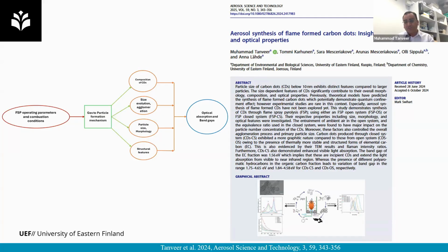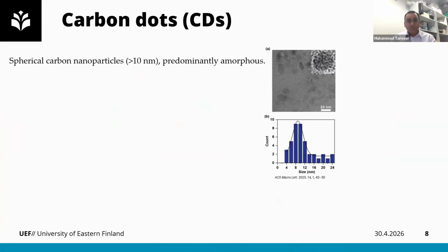In this method, we have used two kinds of configuration for flame spray pyrolysis: open flame spray pyrolysis and closed flame spray pyrolysis. Using these techniques, we have explored the mechanism of particle formation, and then using that mechanism, we have established a structure to property relationship that can give us an idea of how the particle features contribute to the optical properties of the carbon dots. So what are carbon dots? Why are we talking so much about this particular